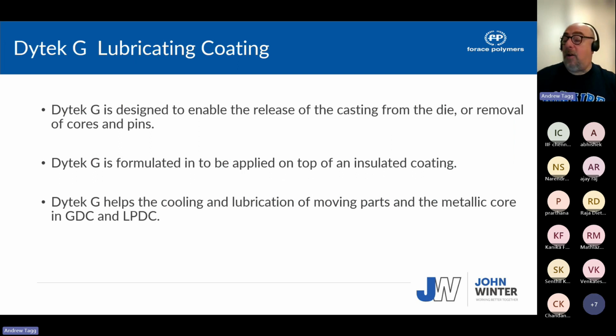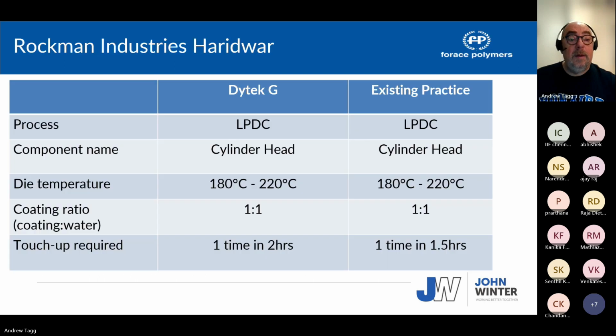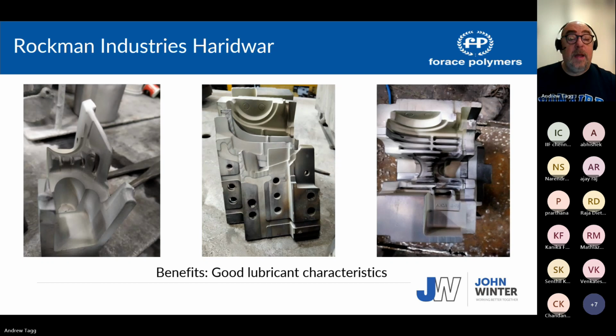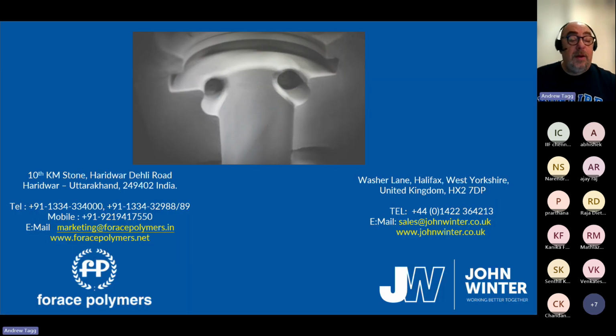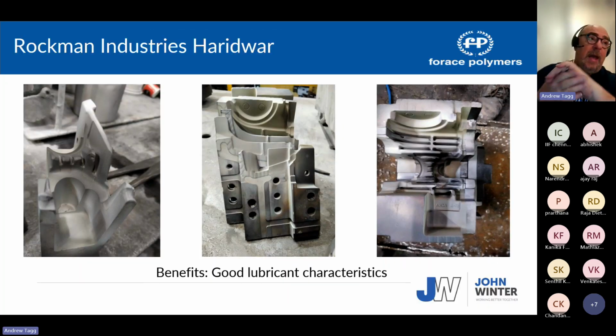We have a lubricating coating called Dytek G, and basically this can be used on a cavity. You would spray it on top of the insulator coating to assist removal of the casting for parts that are difficult to remove from a die. And this was the cylinder head. You can see the graphite coating on the cavity there. It can also be used as a paste for lubricating metal inserts into the die.